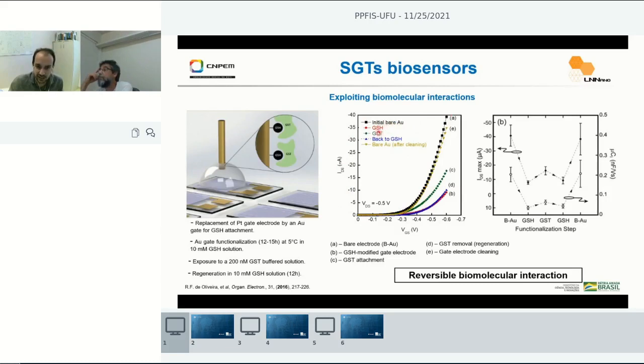And by functionalizing it with the bioreceptor, the current drops significantly because we created a layer of biomolecule here that causes some perturbation to the electrical double layer, reducing the effective gate potential that modulates the channel current. By exposing it to the protein, what we observed is a slight increase of current. That's because this protein is negatively charged in solution, meaning that it induces more p-type carriers in our device.